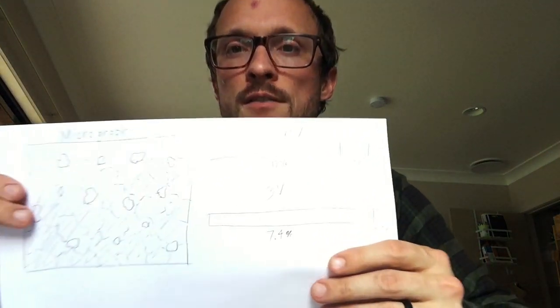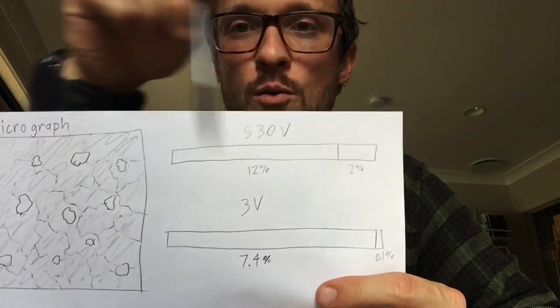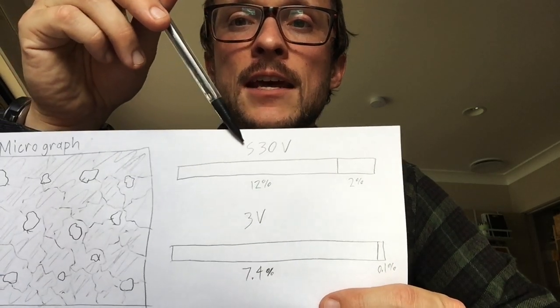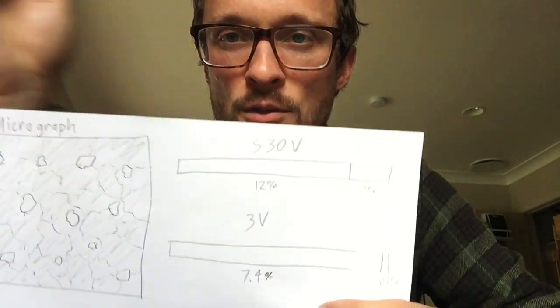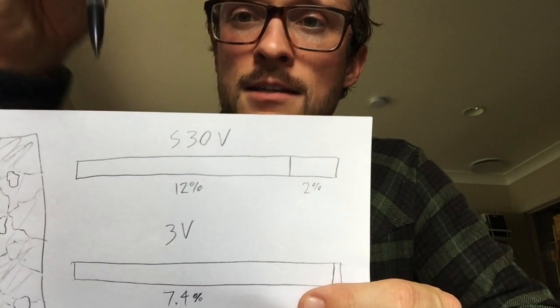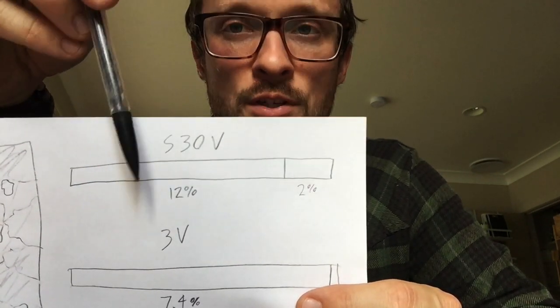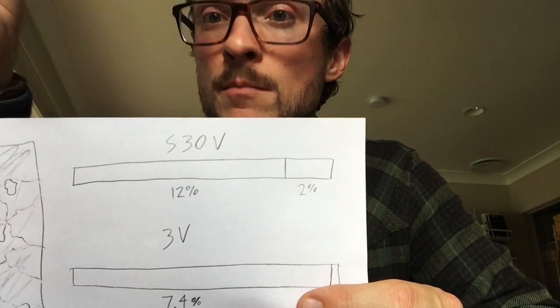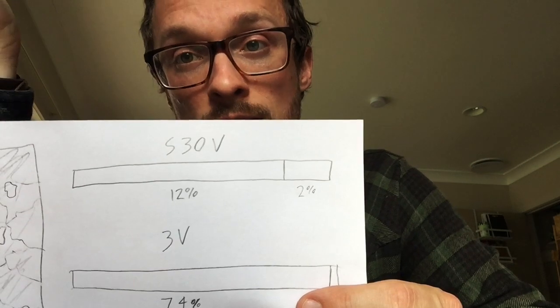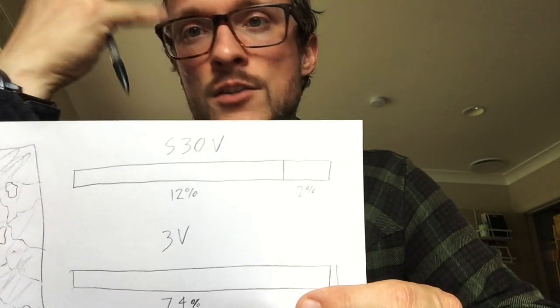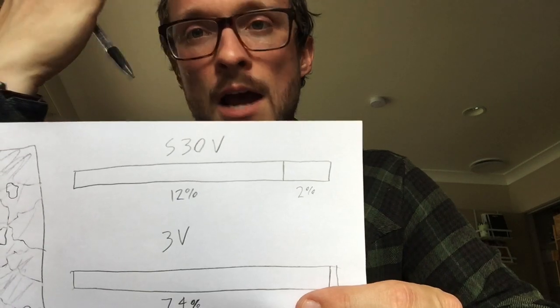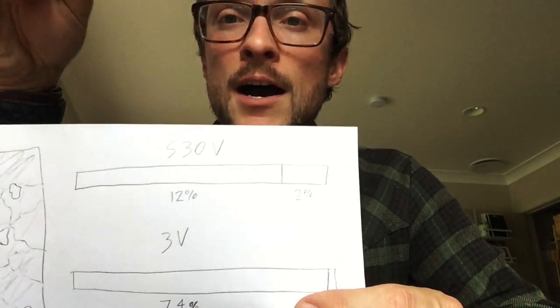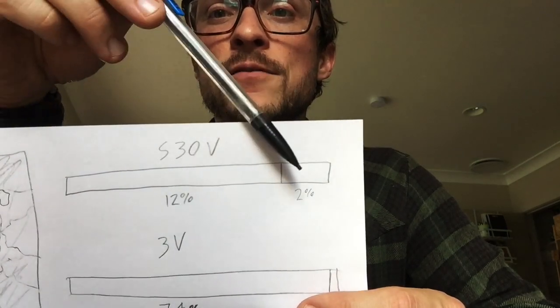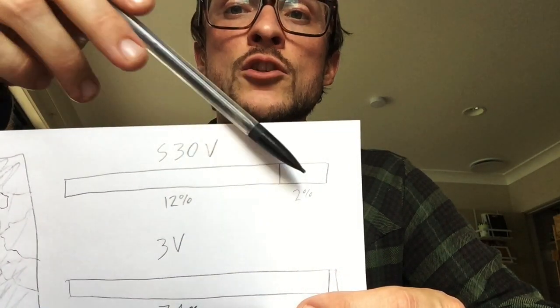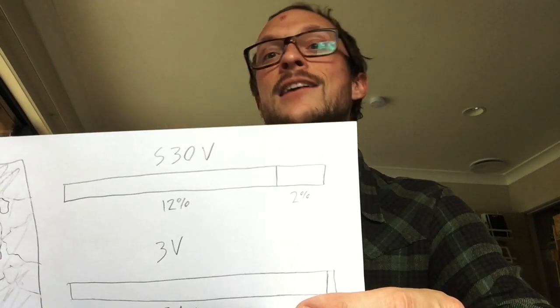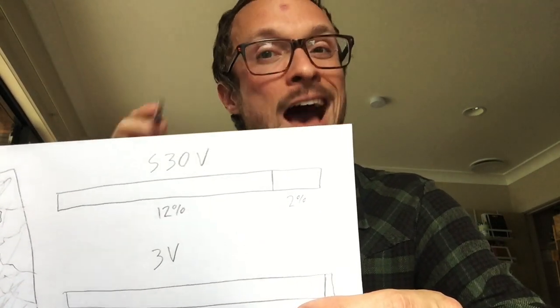So to give an example, if you think of this bar as being the total amount of chrome that's in CPM S30V steel. It has 14% chrome overall, and depending on your heat treat, maybe 12 or 13% of that is going into the steel matrix to make it a relatively stainless steel. And if you've used S30V, you know it doesn't rust unduly quickly or have poor corrosion resistance. But to get that effect, they added 14% total.